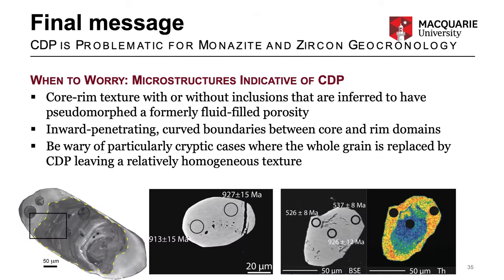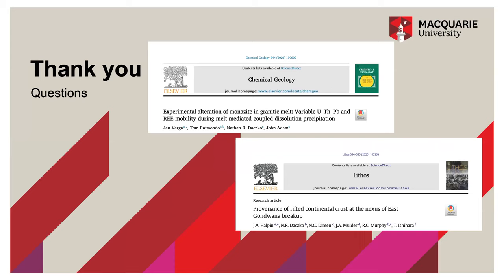So our final message is to ask, when should we worry about this process being a problem for our geochronology? It's when we see microstructures that are indicative of former coupled dissolution precipitation. We might see core-rim textures with or without the inclusions that are inferred to have pseudomorphed a formerly fluid-filled porosity. We might see microporosity and inward penetrating curved boundaries between core and rim domains. We need to be particularly wary that it is possible in cryptic cases that the whole grain can get replaced by coupled dissolution precipitation. And this can leave a relatively homogeneous texture with a complex age pattern. Again, this work has been published for the monazites and for that zircon interpretation in an example from Antarctica.